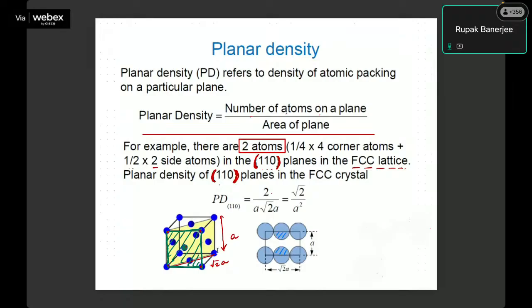And imagine now this distance is actually root 2 times a, because it is a diagonal of this square here, isn't it? So if you look at this, you will see that there are actually how many atomic contributions happening? There is 1/4, 1/4 from the four corners, you get 1 in total. And from these two sitting in between, because of this face centered lattice, you will get half contribution from this atom, half contribution from this atom. So these two will give me total two atoms, one coming from the four corners and one coming from the side atoms. And so the number of atoms on this plane is 2 divided by the area of the plane. Area of the plane is root 2a times a, which is root 2 a squared. So your planar density for the 110 plane is root 2 by a squared.